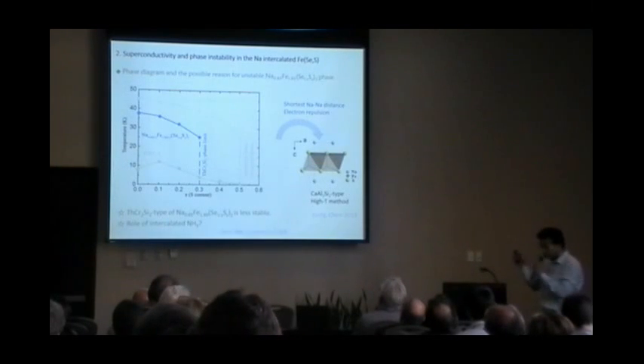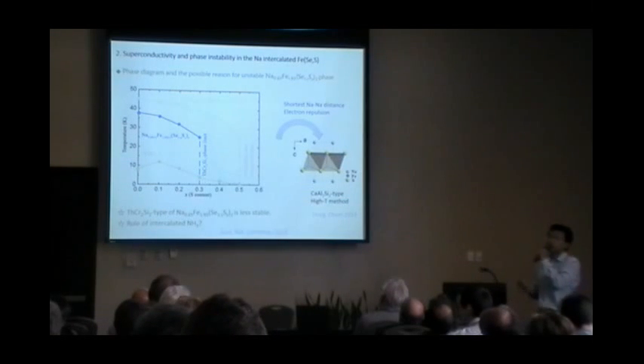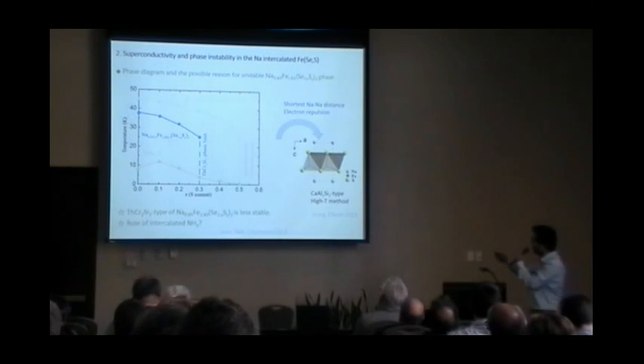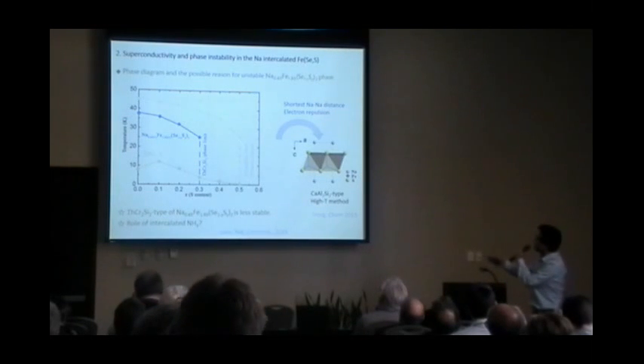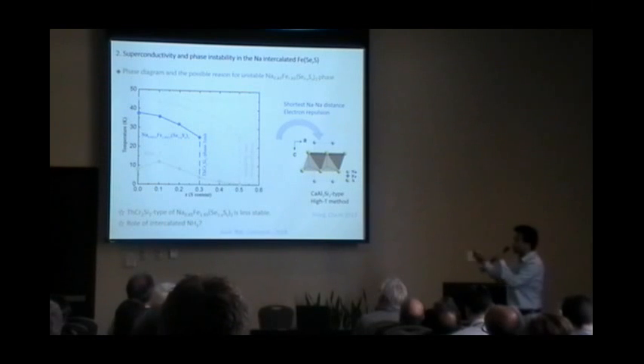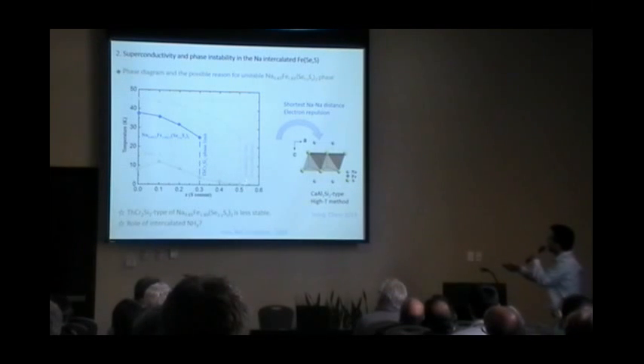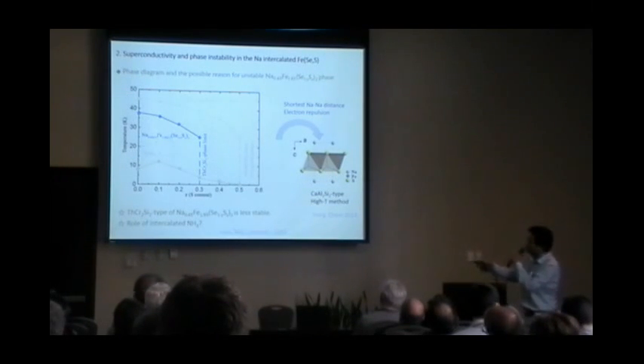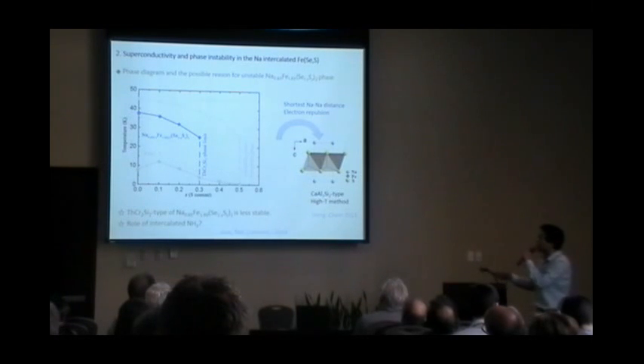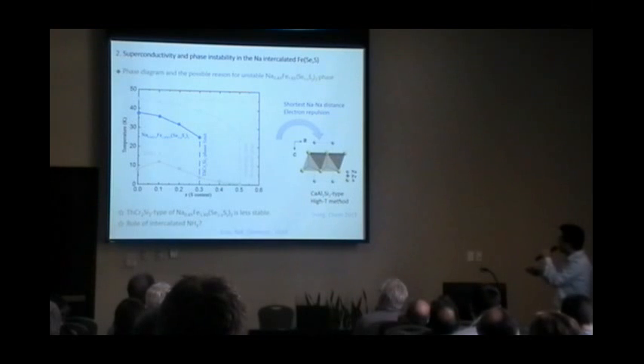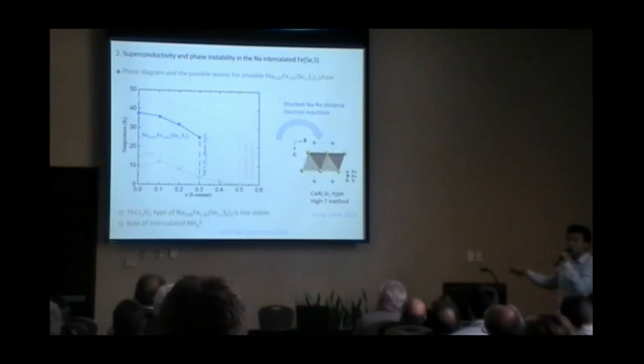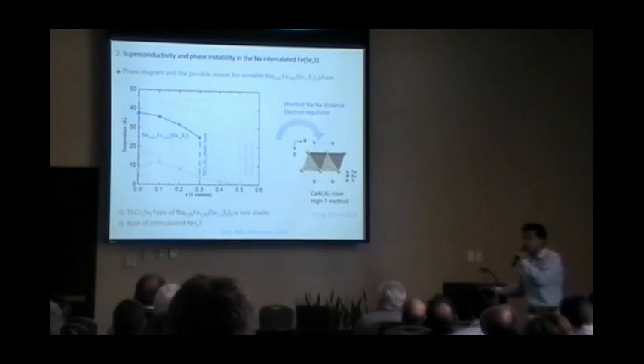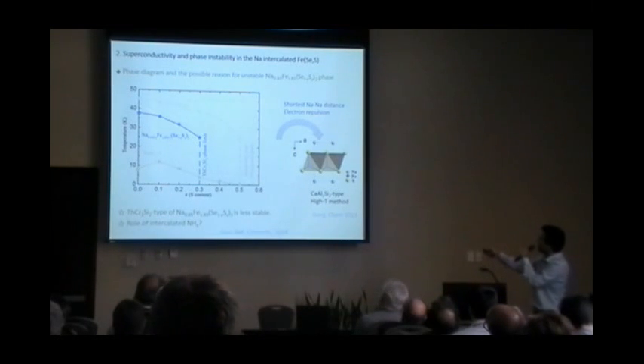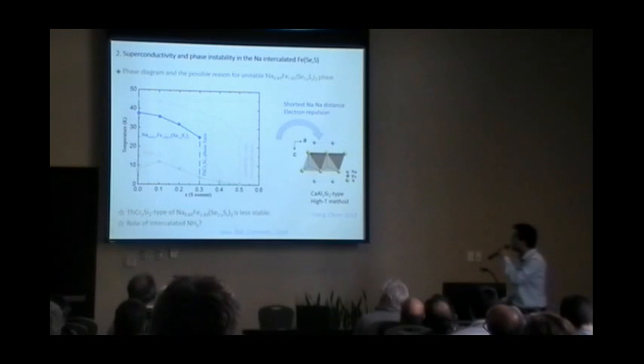After we got these 2 phases, we also examined why the phase is so stable. We can see this curve showing the phase. Containing the ammonia, we can see the phase is pretty stable, up to 0.5. But with the new 1-2-2 phase, we can see the phase range is very narrow. We also found there is a report in 2013 showing that once the selenium is totally changed to sulfur, it's already changed to another 1-2-2 phase. It's not the tetrahedral phase. So this one is pretty narrow.